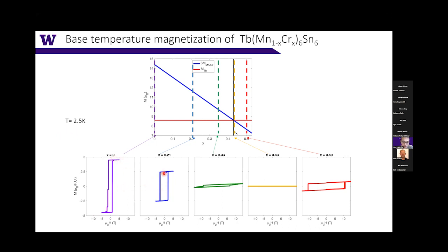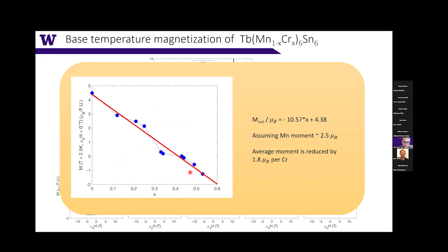And as you increase x, you can see the saturated magnetization progressively decreased, and then eventually almost vanishes around 0.43, and then turns up again at 0.49. So if you obtain this magnetization and plot it as a function of x, treating the magnetization above this compensation doping as negative magnetization, then you can do a linear fit. And what you get is that you're reducing about 1.8 Bohr magneton when you're replacing 1 manganese with 1 chromium. So when you extrapolate all the way to 1, you get about, I think, 0.7 Bohr magneton for the terbium chromium 6 tin 6. So it's not far off from what people have found in the terbium chromium 6 germanium 6.